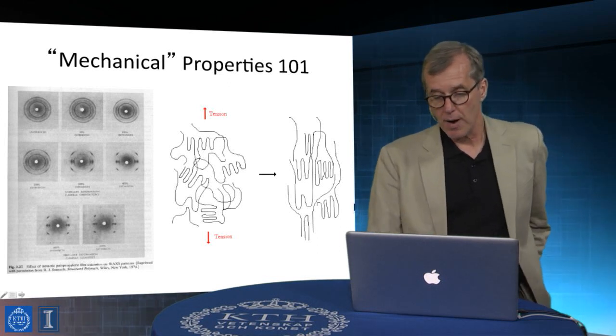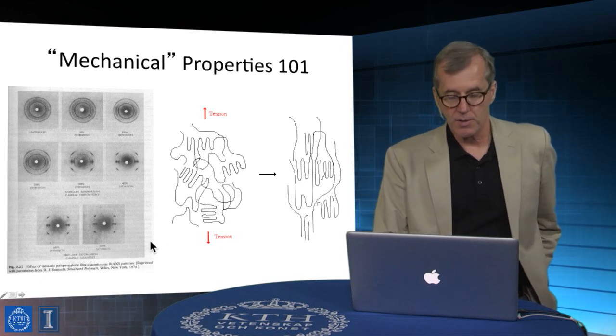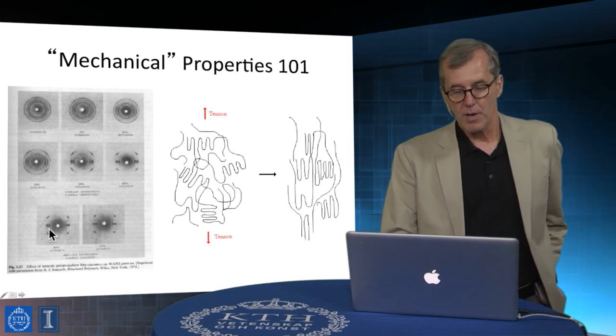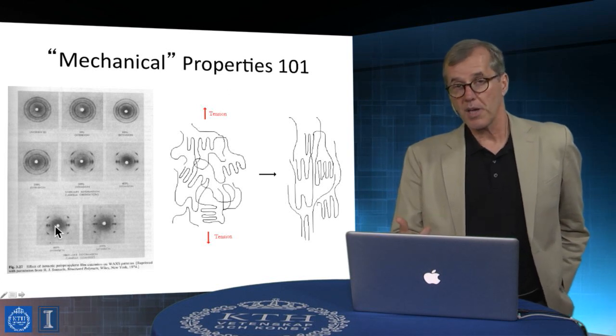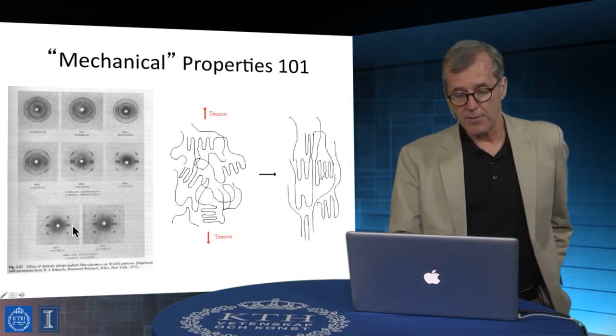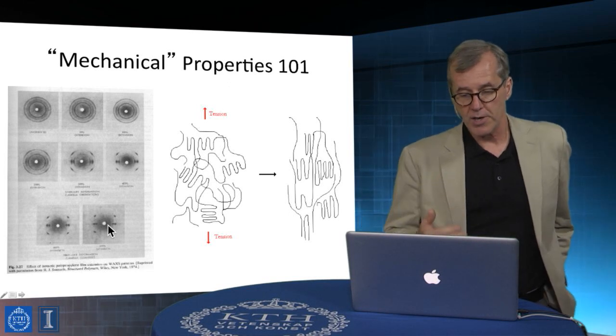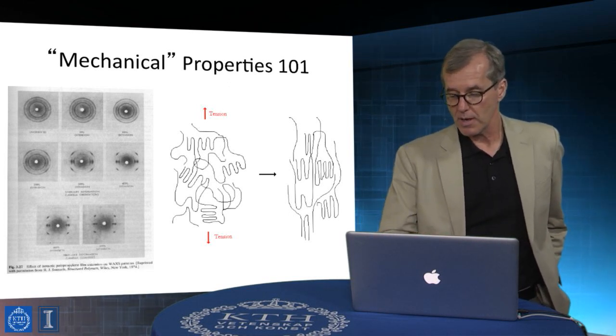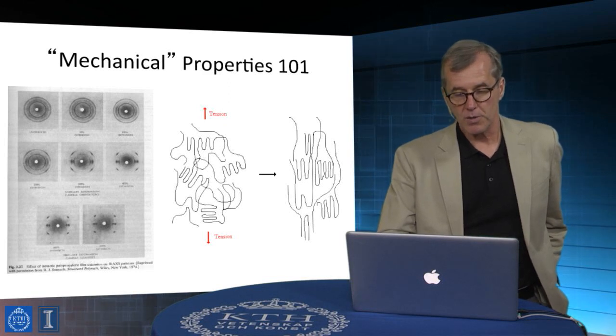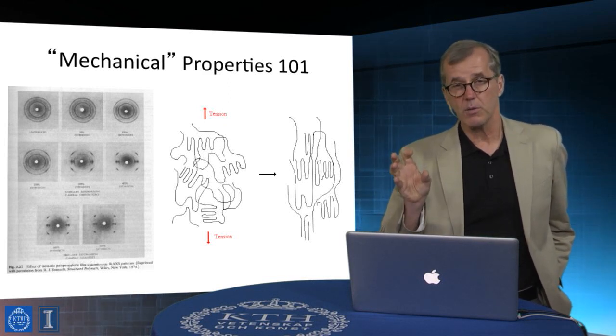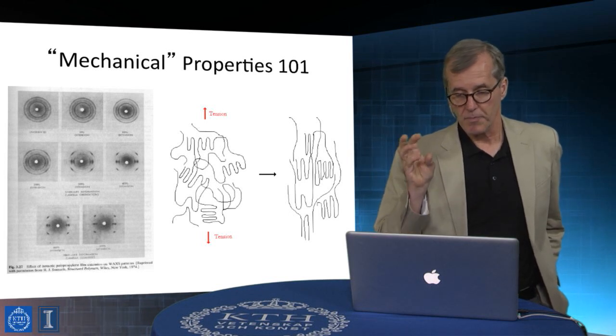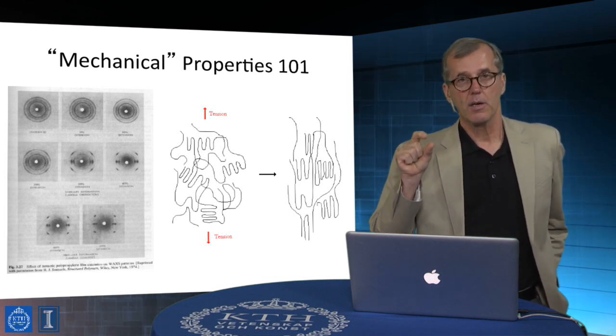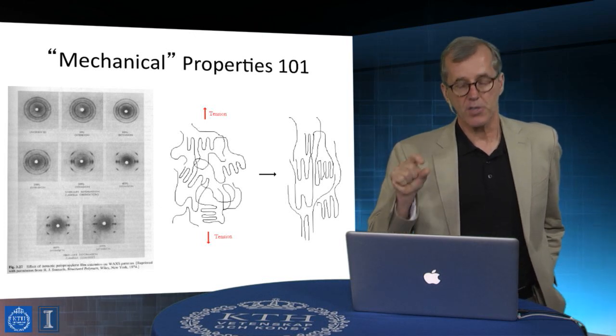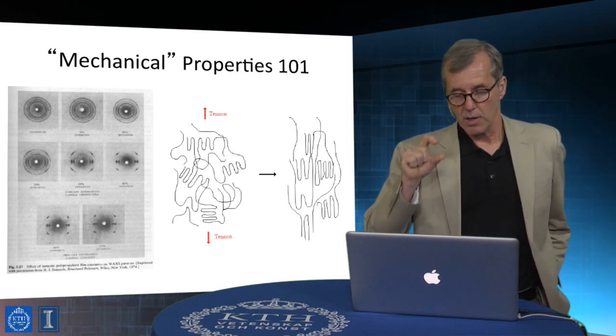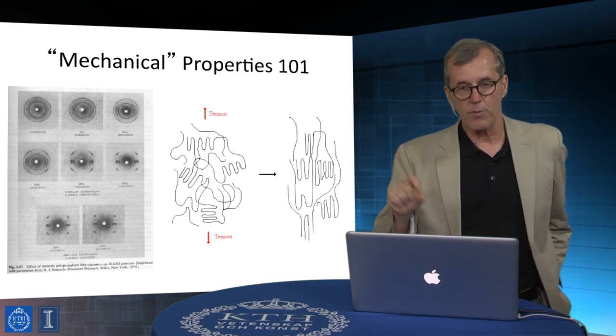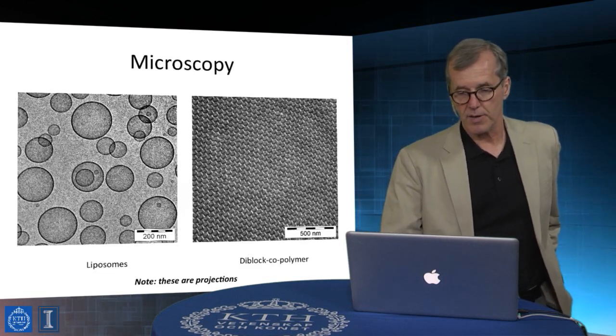So you can measure mechanical properties in that sense to say that these are incredibly strong materials, right? But the understanding of the organizational states that give rise to that effect would come from diffraction and the anisotropies that the X-ray analysis illustrates are occurring, right? Really taking this down to the most discrete attributes of molecular organization in coherent form, in long-range translationally ordered forms in a crystalline phase.